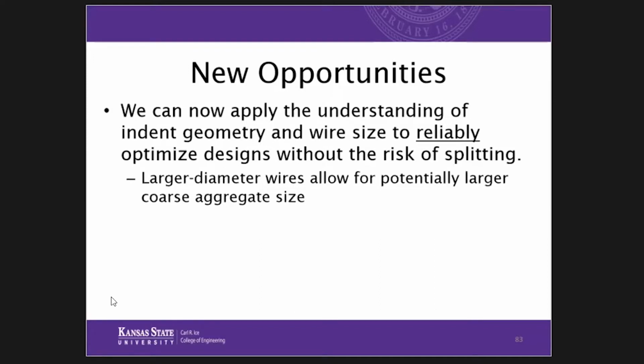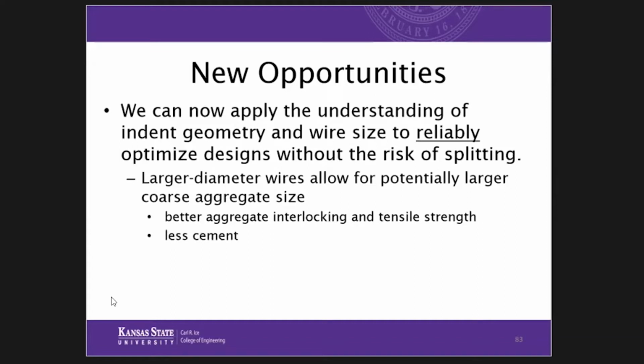So why would we want to use a larger diameter wire? Larger diameter wires allow for potentially larger coarse aggregate size. If we don't have the wires as close together, we can get bigger aggregates down. Bigger aggregates are an advantage for several reasons. We get better aggregate interlock within the tie if we allow bigger aggregates to get through. We have less cement demand. The cement has to coat all of our smaller particles. So if we have some bigger aggregates in there, we up our distribution size, we're going to have lower cement demand. Also, we're going to have lower creep and shrinkage. So I think allowing for larger coarse aggregate would be beneficial. It also allows us to innovate new designs.